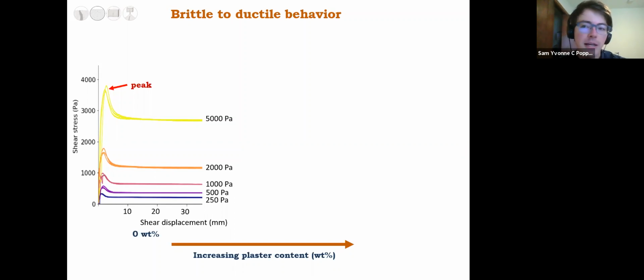On the horizontal axis, you got shear displacement of the sample, and on the vertical axis, you got the measured shear stress. And those different curves represent increasing normal loads which are placed on top of the experiment. And it was well known for pure sand that as you start deforming the sand, you will very quickly increase the shear stress to a peak at failure of the material, where you localize a shear plane and then decrease to a kind of stable strength.